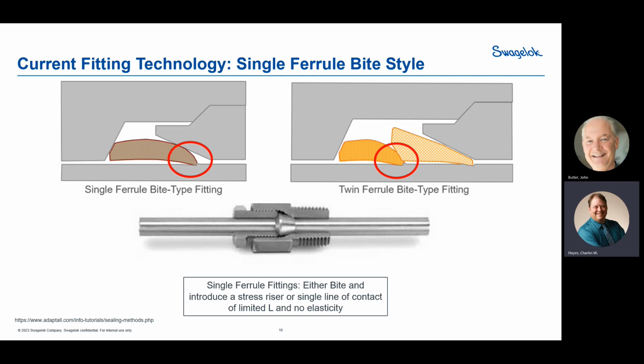It causes a fairly significant stress riser that if you end up putting a load side to side on this tubing from behind, that stress riser can actually cause a crack and it could fail right there. So bite style is not good, especially in our vibration situations. Next one is, of course, the old, for our Americans, Home Depot, for Canadians, what is that, Canadian Tire? Your local hardware store makes stuff to go under your sink, usually in brass, usually not very good quality, and it'll be a single ferrule, and it relies 100% on friction, so it's just a friction fit. Not a great idea. Do not use it with nitrogen. Again, there's not enough energy there, not enough design to be able to hold that entire load back, especially at high pressures.